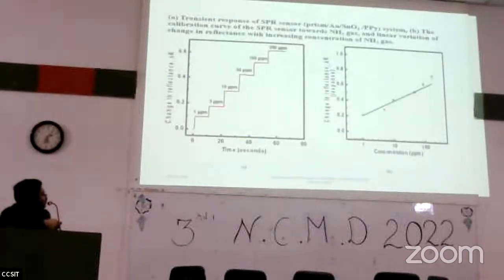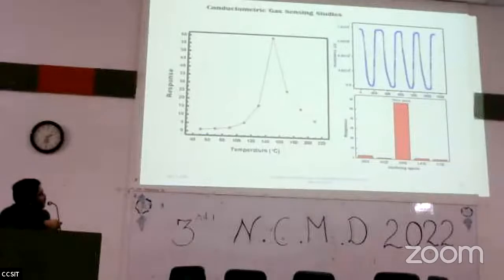So this is our dynamic study for the proposed sensor. Again, we obtain the calibration curve. So this is the conductometric study. It was observed around 150 degrees Celsius. This SnO2 has a good sensor response of 60, and repeatability studies were also performed. It shows a good result. Interference studies of various other gases, for example SO2, NO2, LPG, and other gases were also performed. For ammonia, it was maximum.